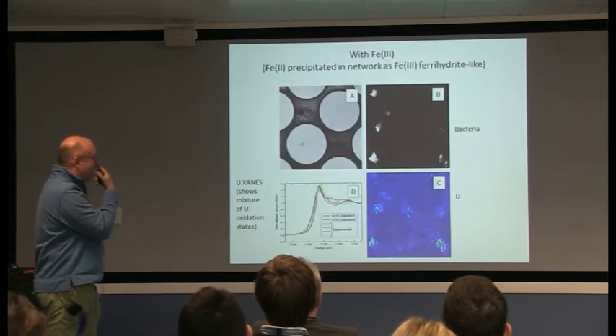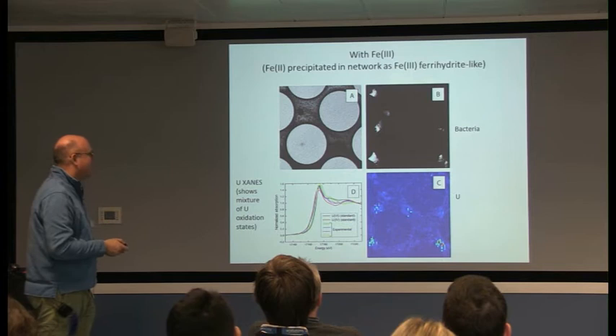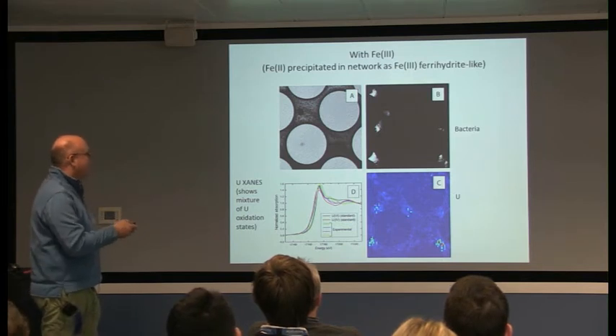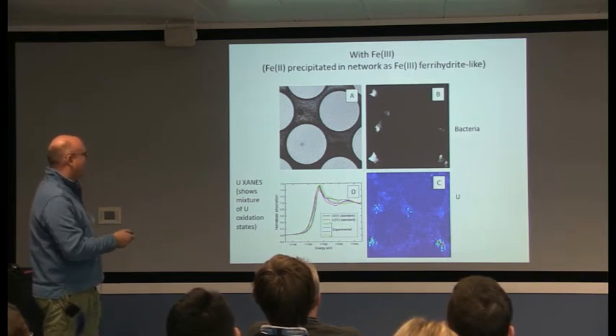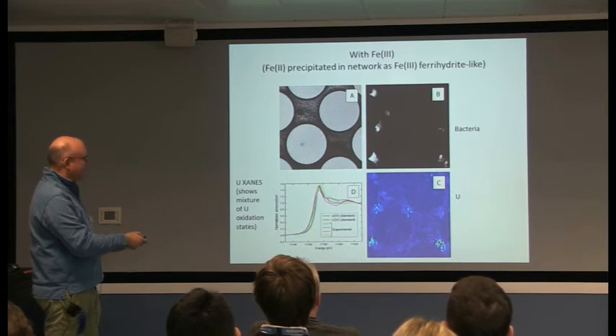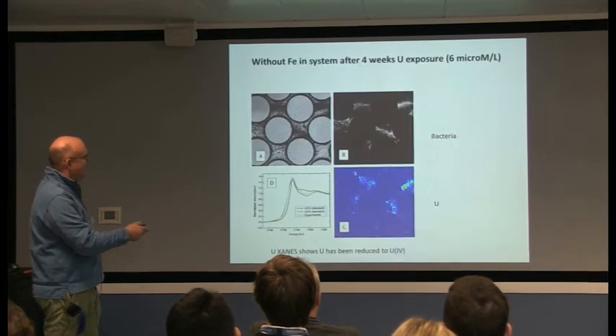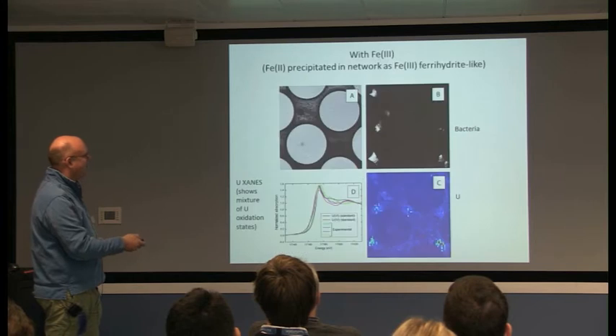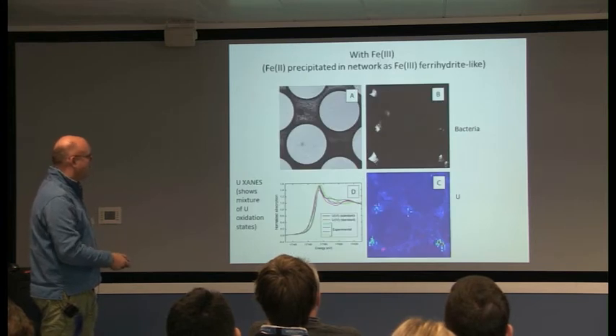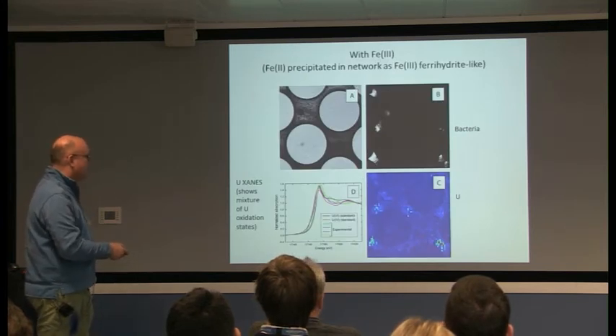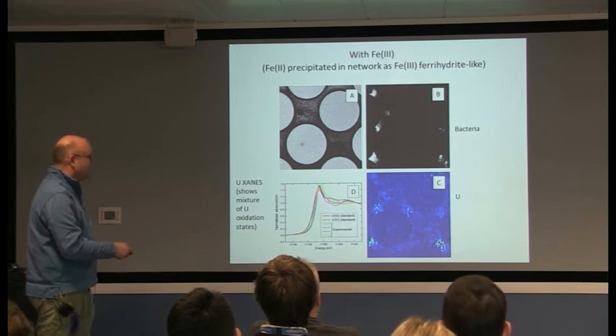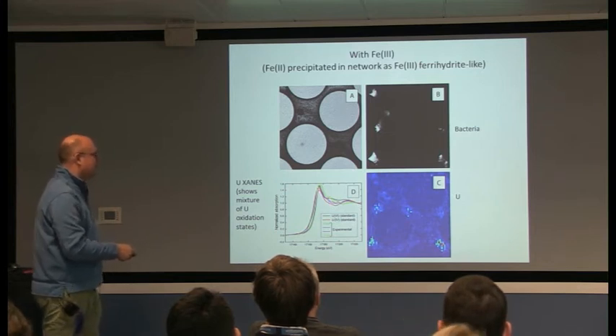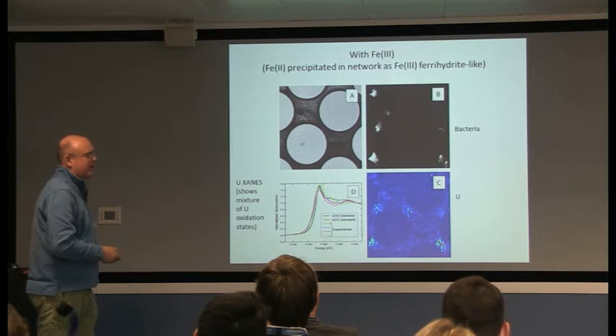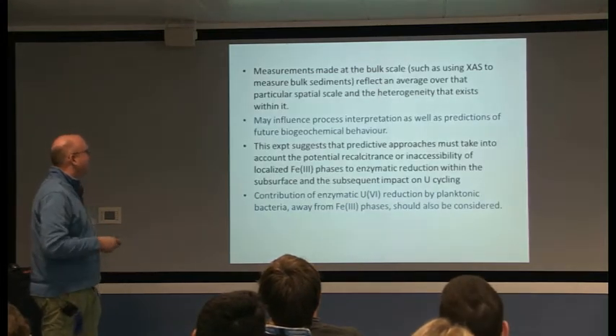Then if you add iron, you get some iron precipitating in the network, and now you can see the uranium is reduced here, but it doesn't necessarily stay perfectly aligned with the bacteria. Here it really stays well aligned with the bacteria, but some of the uranium is not reduced here, some is still uranium-6, so there's less reduction when you've got some iron around.